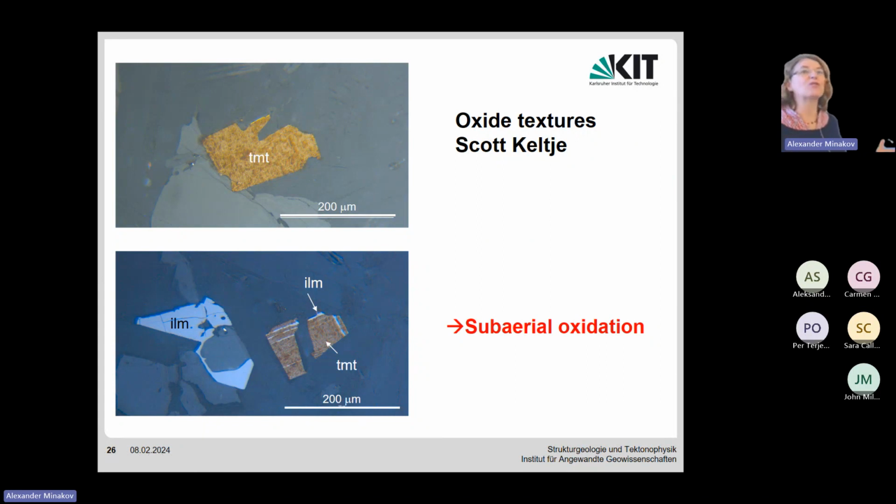It's a quite coarse-grained basalt, yeah. So that we see here, and this is also seen in the oxide textures. It's what I've done here. I've coated the polished thin sections with a ferrofluid. And with this, we can see the magnetic phases, titanomagnetites here, more clearly, and we can distinguish them from the ilmenites. So we have here ilmenite and here magnetite, and we see these exsolution features.